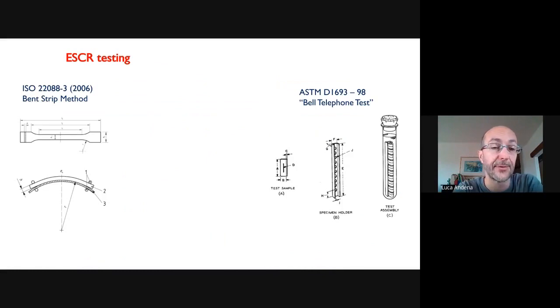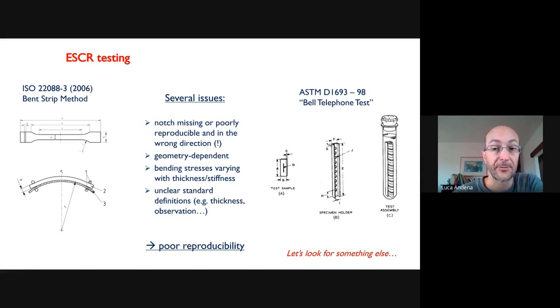There are a few issues with this kind of test. As you may notice, none of them is a proper fracture mechanics test. In a bent strip method, you don't have a notch. So the defect which originates fracture is not known a priori, it depends on the defects left there by the production process. In a Bell telephone test, you have a notch, but the notch is put in a wrong way when you compare it with existing bending stresses, which would be parallel to the notch direction. So the notch will cause the initiation of fracture, but then the fracture will proceed driven by stresses which are not the bending stresses and would change direction.